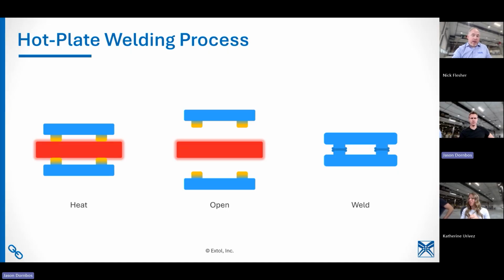So Jeff gives some context there. They are using a copolymer. Copolymers really are also a wide range. We have seen strength of copolymers can be a challenge, as can sticking. We do have some sticking sub-processes. I won't get into the details of those, but microtoming, if you're not familiar with that term, is an ultra-thin slice, and you can inspect the heat affected zone, the melt zone, and how much material is remaining there, so you're not doing cold welds.